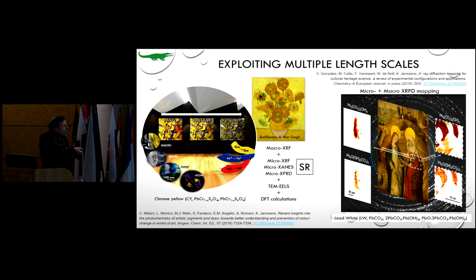Then on the nanoscale, you can look at nanoparticles of lead chromate, the chrome yellow in here, with TEM. And then on the atomic scale, you can, for instance, do DFT calculations to figure out some stable or not so stable configurations. And a bit less full range is going on now, for instance, on what's happening to lead-white components, where certainly the macro and the micro level can be confronted with each other and the insights combined.